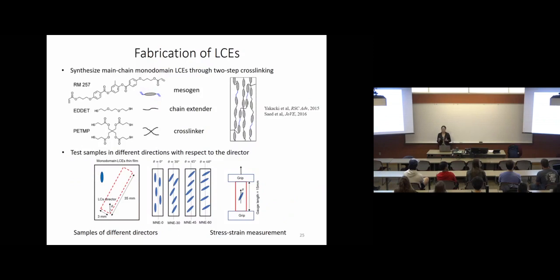Here we fabricate liquid crystal elastomer following the literature, to synthesize monodomain main-chain liquid crystal elastomers through a so-called two-step cross-linking process. In the film, we fabricate the director aligned in a certain direction, but we can cut the sample into long strips or different shapes at different angles with respect to the director. Then here I'm first testing some homogeneous behavior, therefore I'm uniaxially stretching the material.